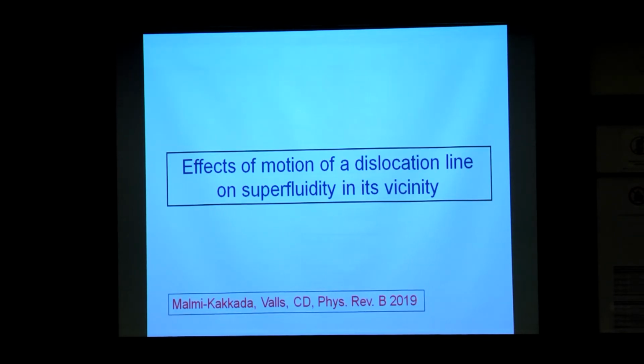Okay, so this is pretty much one of the calculations that we did. Again, the conclusion is that if you have a system of bosons in 2 dimensions with appropriate interactions, then it will or should exhibit a phase which is polycrystalline, and then there are grain boundaries, and bosons near the grain boundary can become superfluid. So that system can show this non-classical rotational inertia if these superfluid channels form, join together and form closed structures of size comparable to the system size.